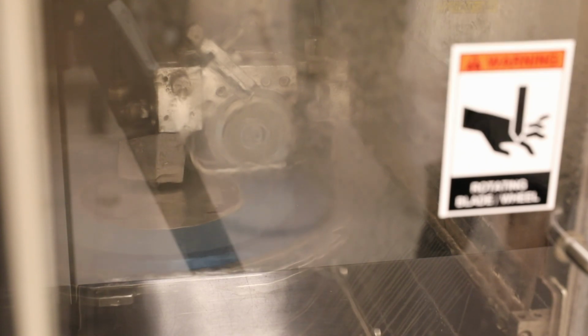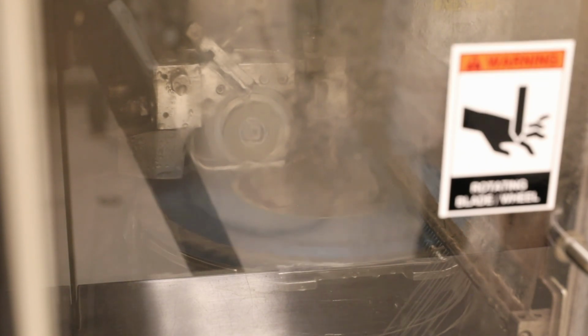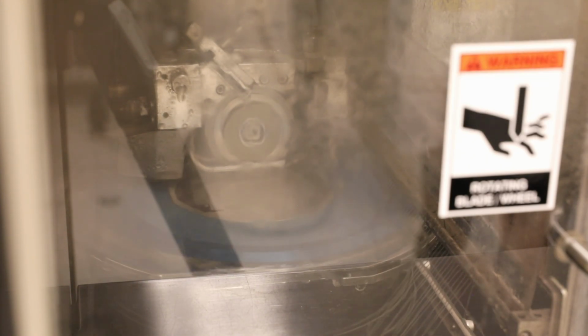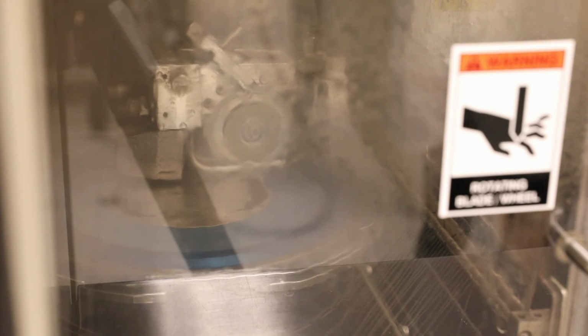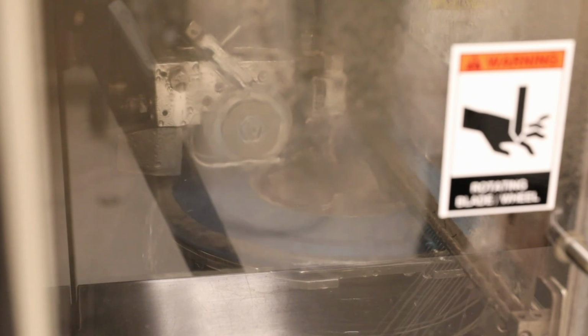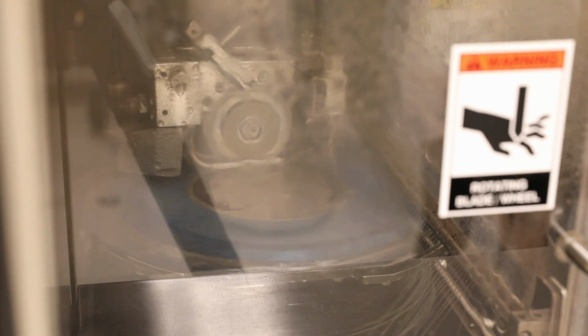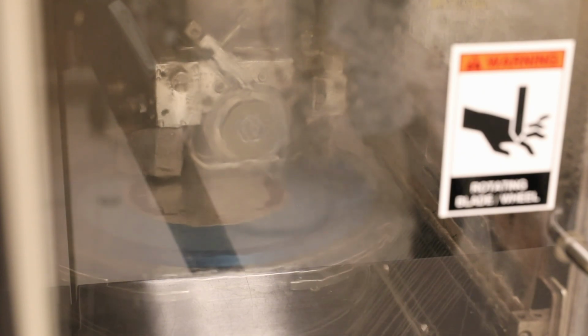You see that there is quite a strong stream of water flowing constantly against the blade, and that's because things get pretty heated during dicing, so we need to use cooling water to avoid overheating as well as to remove debris. This strong water flow is why it is very important to attach your wafer properly to the mounting tape, so as not to suffer great material and emotional losses.